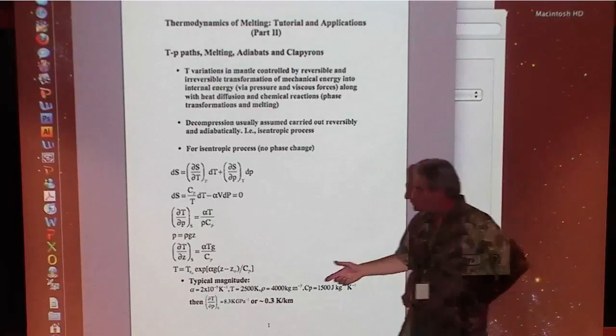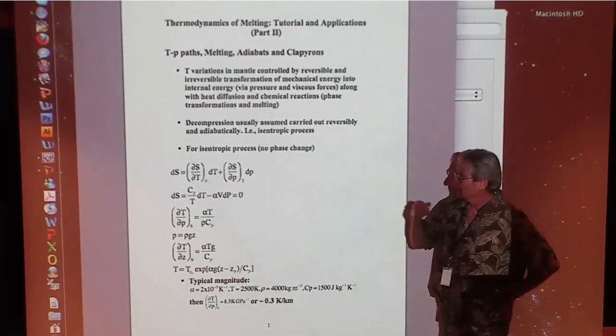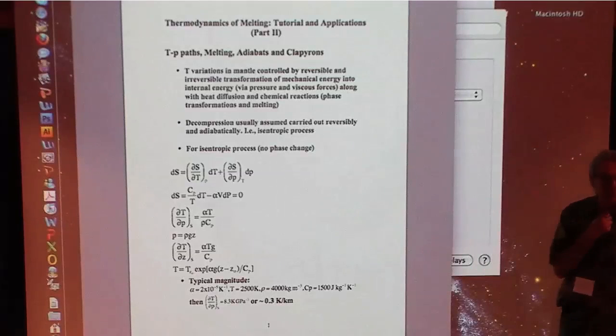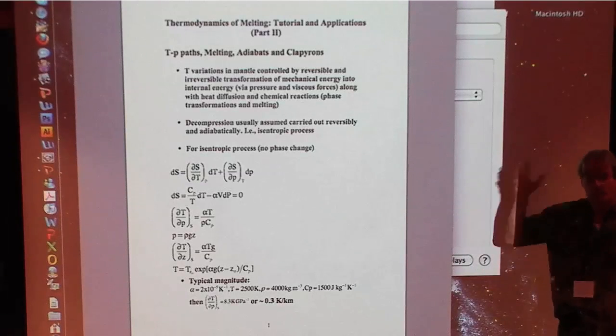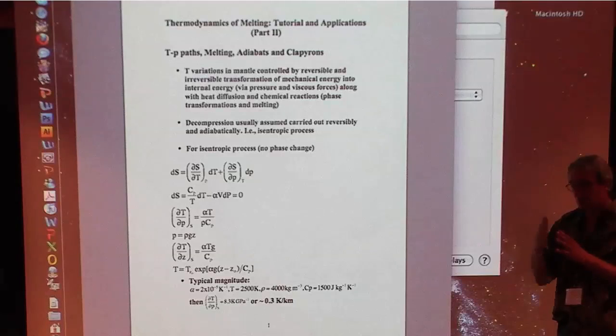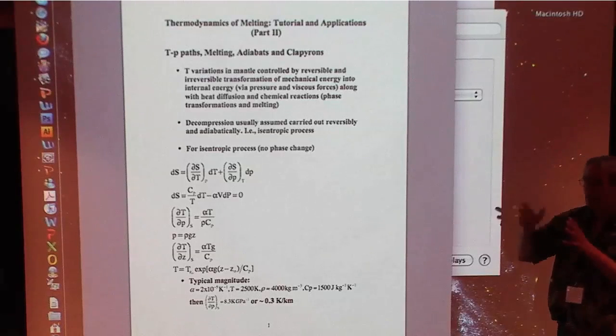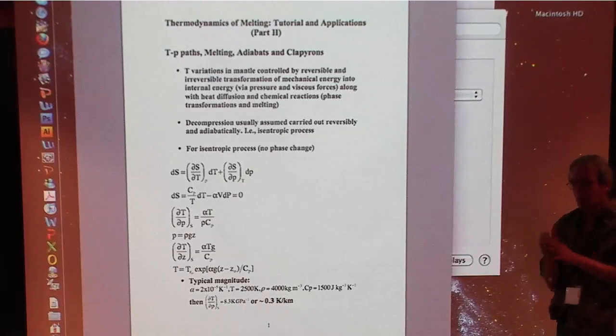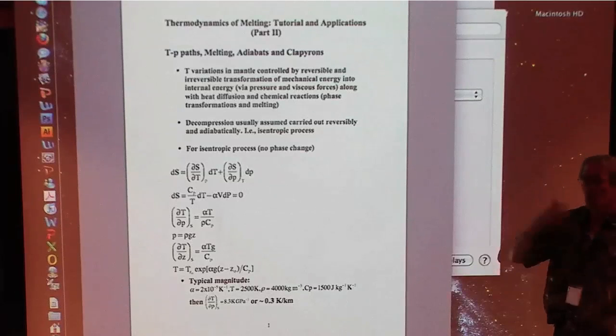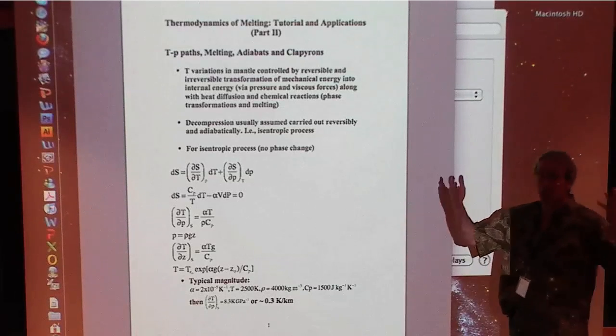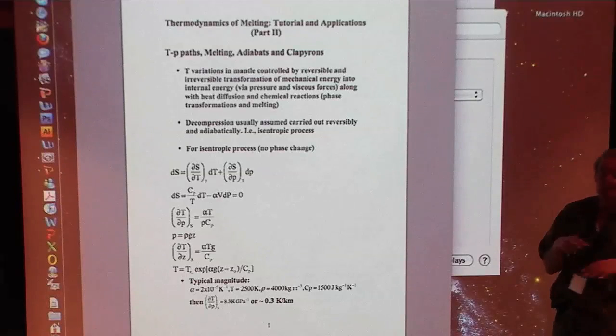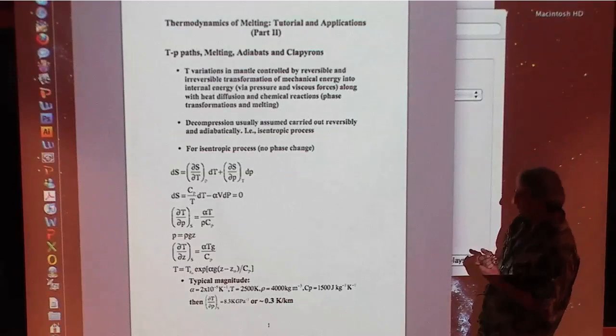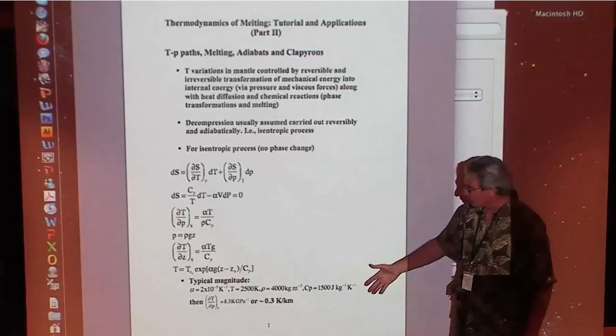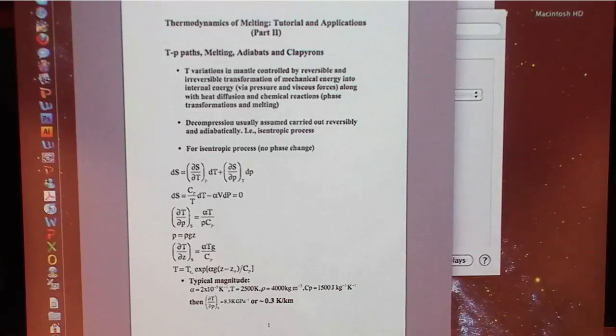I think on the next slide I may write this in terms of... Oh, I'm sorry. Yeah, the Grüneisen parameter is nifty because it's roughly a constant. Changes with pressure and temperature. And at the next level, it depends on volume, not so much on temperature. And then at the next level, it depends on the whole. And then composition. Oh my God, now you're really screwed. But it's a nice vehicle. Anyway, so typical isentrope here is 0.3 degrees per kilometer. Just putting in some typical values for silicate solids.